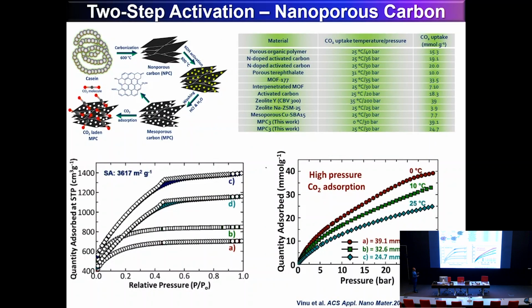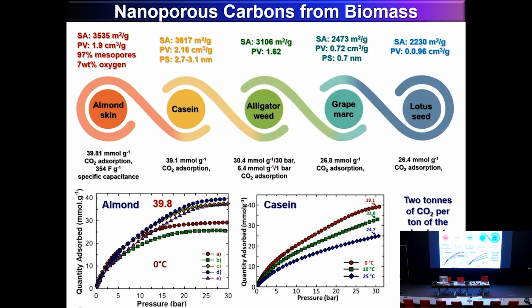And then we dope that high surface area carbon material with nitrogen. How do we do that? We use the casein, which has a lot of nitrogen, and then integrate it with the two-step activation, and you get a material with a very high surface area of both microporosity and mesoporosity. And what we found in the CO2 adsorption is almost 2 tons of CO2 per ton of the material, which is much better than the other porous carbon-based materials, right?